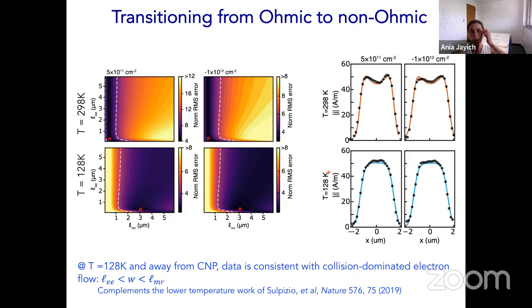Okay, and quantitatively, we've analyzed these data sets to extract our best fit for the momentum relaxing and the electron-electron scattering length at these different temperatures and these different densities. What we see here is that at 128 Kelvin, away from charge neutrality, I'm not showing the charge neutrality here because it's ohmic and we expect it to be ohmic, for these finite densities the data is consistent with collision-dominated electron flow, this regime where the electron scattering length is small and is dominant.